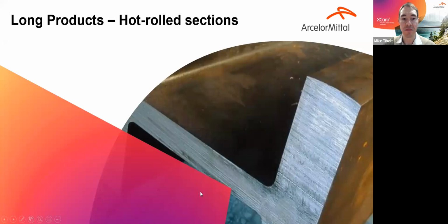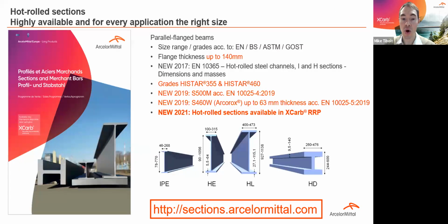On the next slide, we see some hot rolled sections, which are available under the X-Carb Recycled and Renewably produced brand. So on the next slide, we see an overview of these sections. All of our sections available in our sales catalog, from the IPE over the HE, HL to HD, which are the jumbo profiles, with flange thickness up to 140 millimeters, and also our steel grades HISTAR, like the HISTAR 460, where we have a minimum yield strength of 460 megapascal up to a flange thickness of 100 millimeters. Also steel grade S500M, which is new, and also weathering steel, which for hot rolled sections is called ARCOROX, up to steel grade S460W and a thickness of 63 millimeters according to the corresponding product standard, are all available under the X-Carb Recycled and Renewably produced brand.